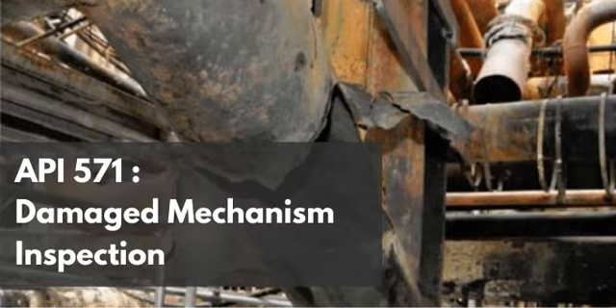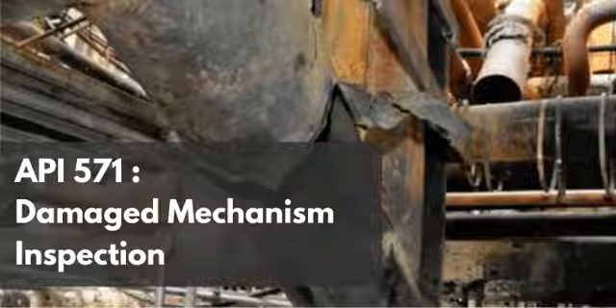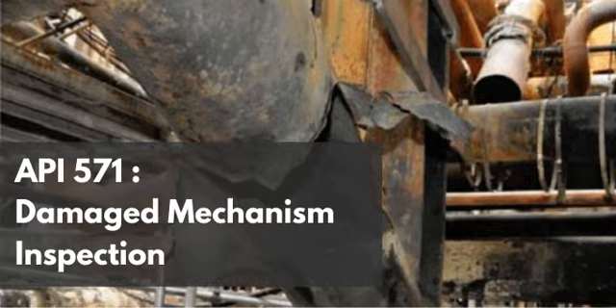Because of the thermal mass of the 36-inch pipe. When you strike an arc to weld that tiny bracket, you introduce a localized spot of 3,000-degree heat. Right. But the massive steel wall of the pipe acts as an infinite heat sink. The moment the arc stops, that tiny weld pool is quenched by the surrounding cold steel at an incredibly rapid cooling rate. Which creates an extreme state of thermal contraction and potentially forms a hard, brittle microstructure in the HAZ. Yes, you have just created a hyper-concentrated high residual stress zone on the pressure boundary of an active amine line.